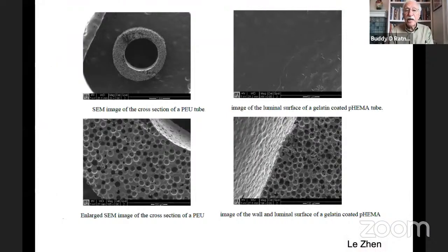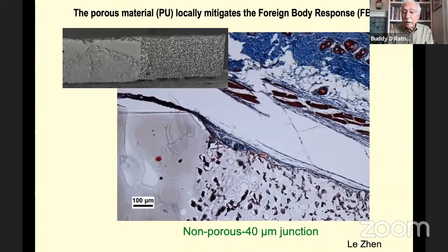So this is just some SEMs showing the wall structure and what this material actually looks like. And Le Zhen made this unique implant. The left side is a solid material of this polyurethane. The right side is this unique porous structure. It was implanted for a month, in this case subcutaneously. And on the left side, if you look at the histology image, you can see the dense blue line from trichrome staining that's indicative of a dense foreign body capsule.